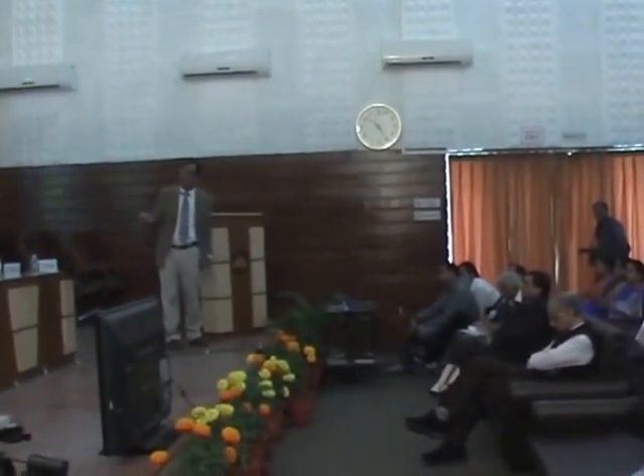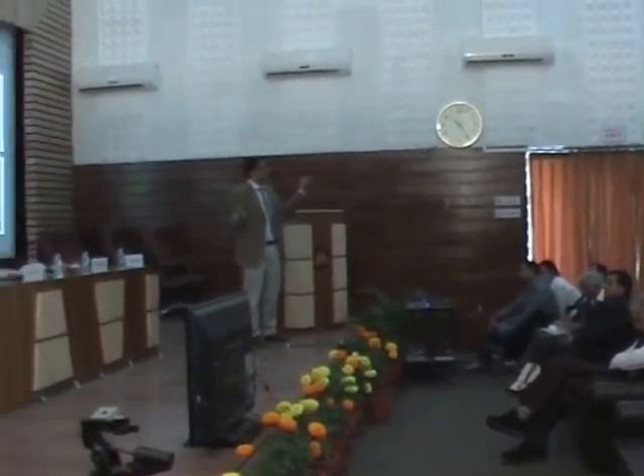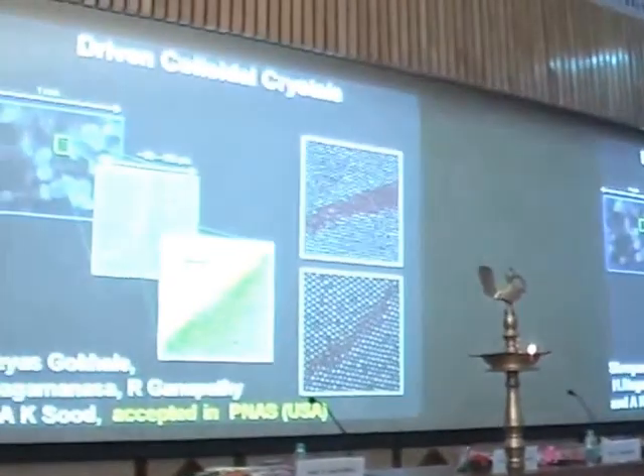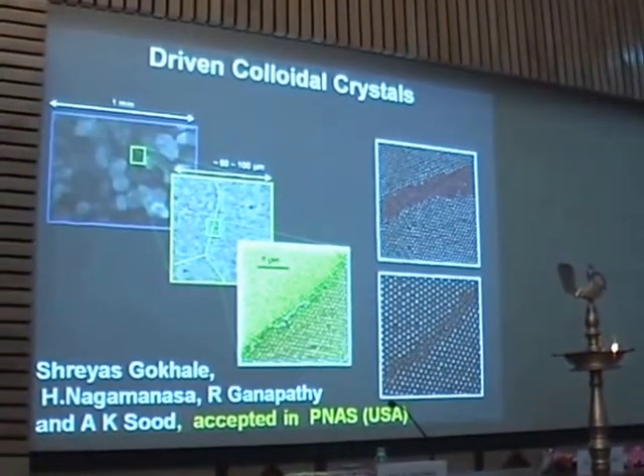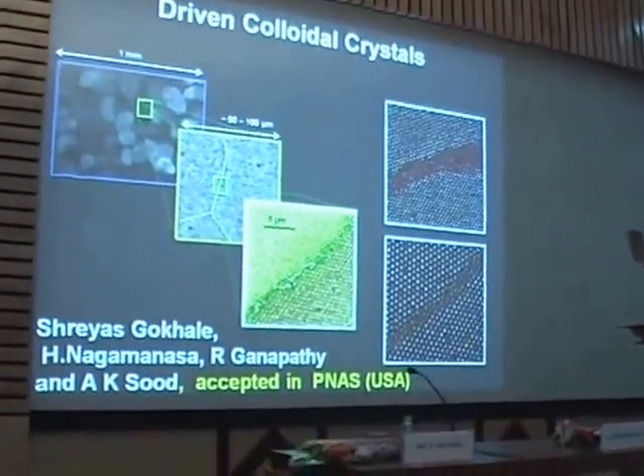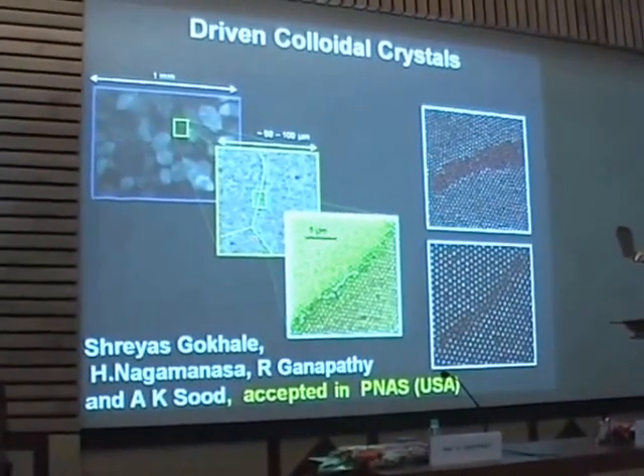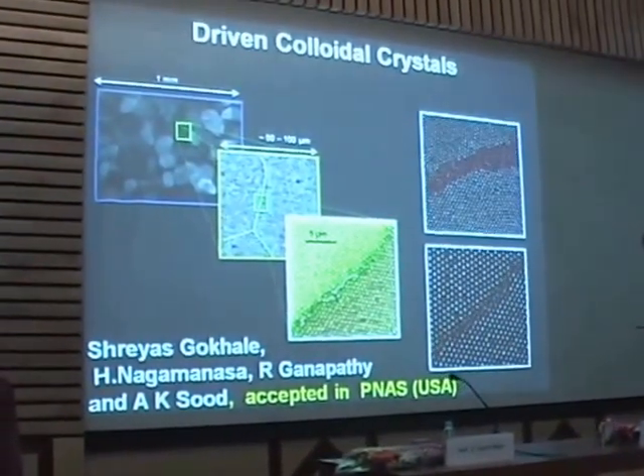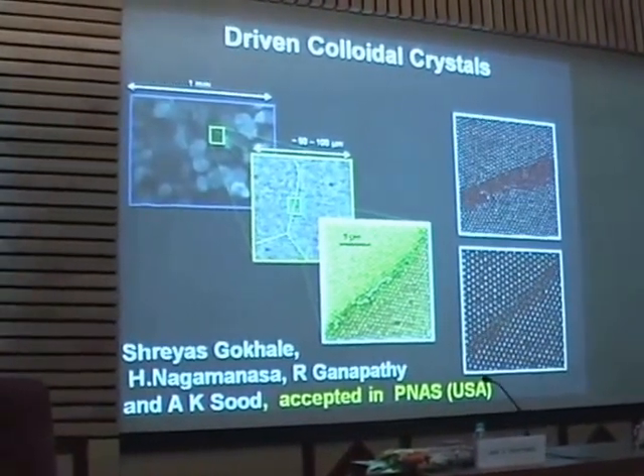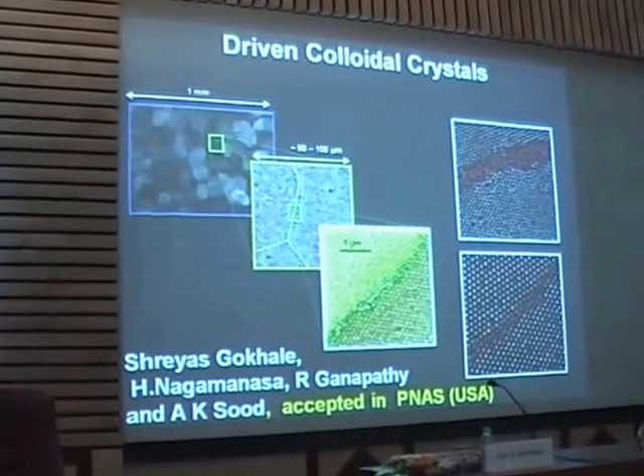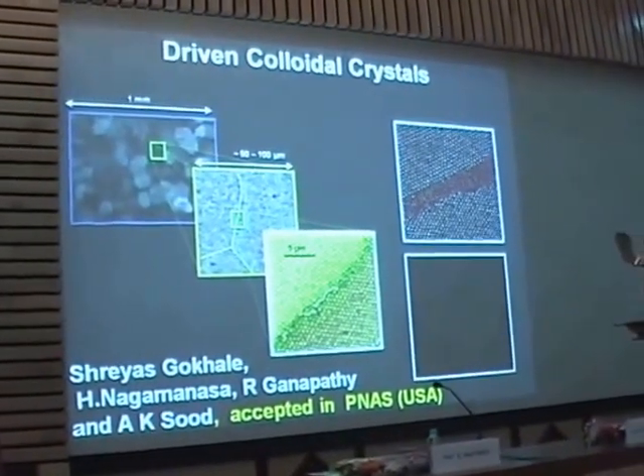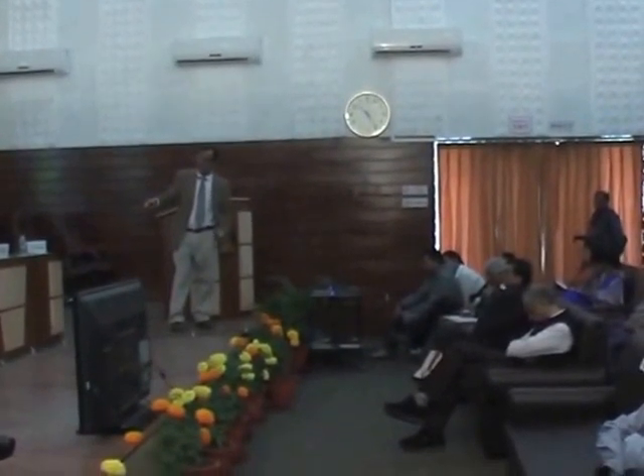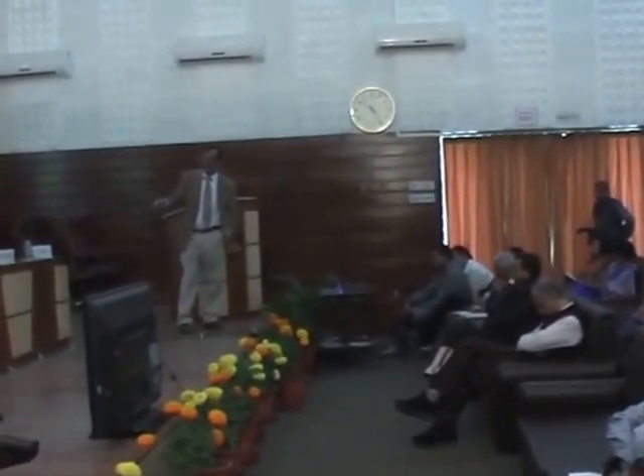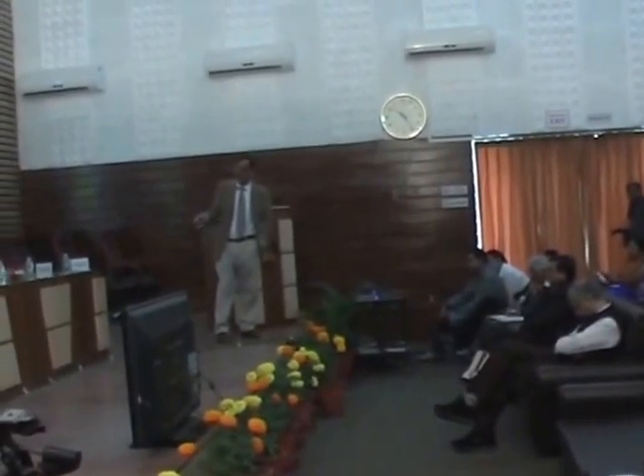Now here, when they form a crystal, it is not a single crystal. You can have these crystals which are a few microns big, and this particle is 1 micron, so the crystal can be about 10 micron to 20 micron, and there are many of them in the sample. But now if you look at the grain boundary between these two, this grain boundary is almost like a glass. So in the next 5 minutes, I'll tell you what is exciting about these crystals, because there is a lot of science to be understood about how these grain boundaries behave. And this is the work which will appear probably in 1 or 2 months in PNAS.